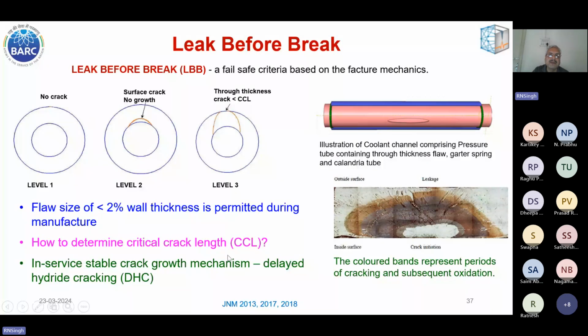And the in-service crack mechanism, delayed hydride cracking velocity, is there. So by using the fracture toughness, CCL obtained from fracture toughness, and DHC velocity obtained from the delayed hydride cracking test, one can assess whether these tubes will fail by leak or by break.